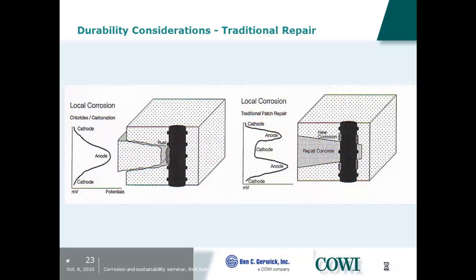We did some studies for Fosroc nearly 10 years ago, where on different structures we measured how much current they could actually give and what the chloride concentration was, and we also measured the performance of them. Based on that, we said that they cannot overcome everything. If you have a high chloride concentration, they would not be able to provide enough current, and at the same time it would be consumed faster.